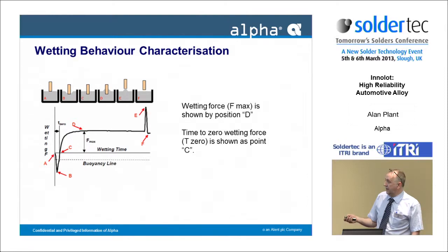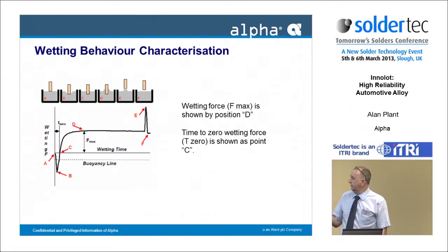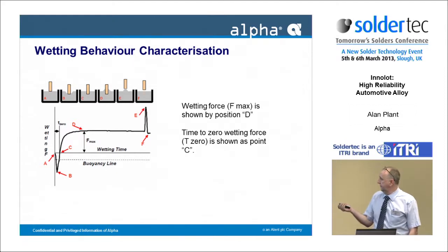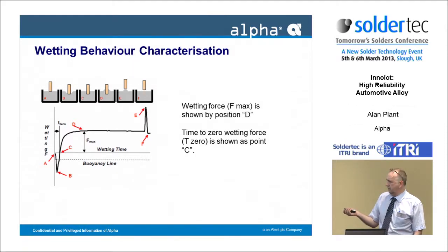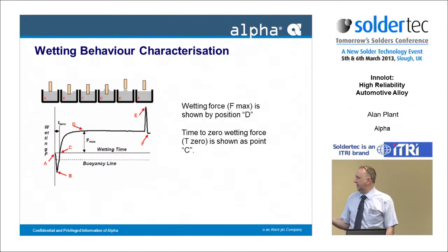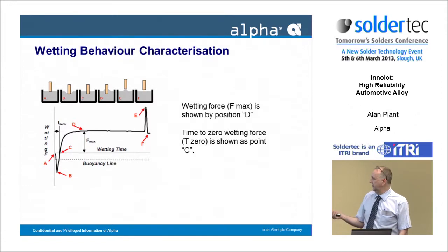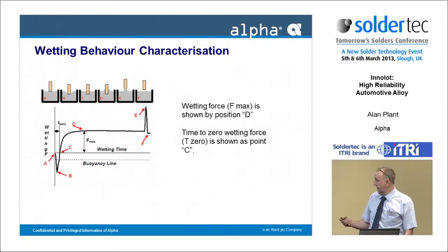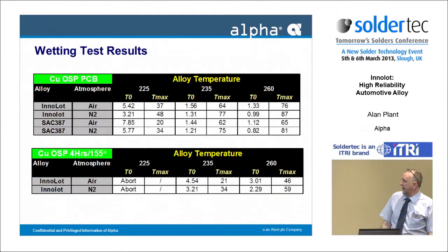Gradually it'll start to heat, it'll start to wet out, and you reach a point here, C, which we can measure as the time to zero wetting force. Sometimes people do these to time to 2/3 of the maximum wetting force. They tend to give you fairly similar results, and then we've got the maximum wetting force there.